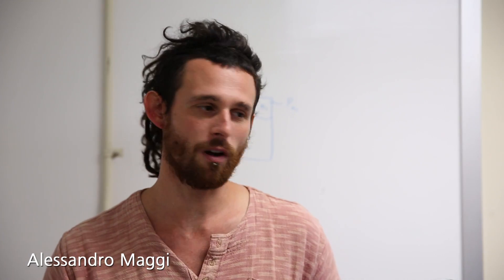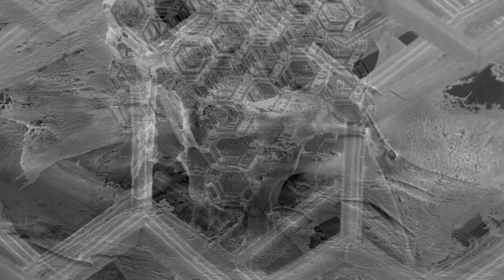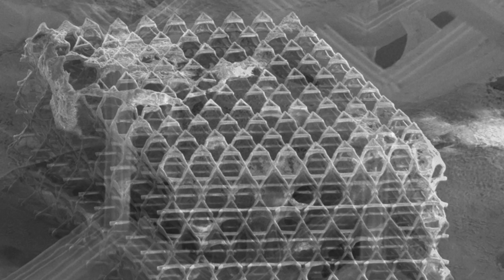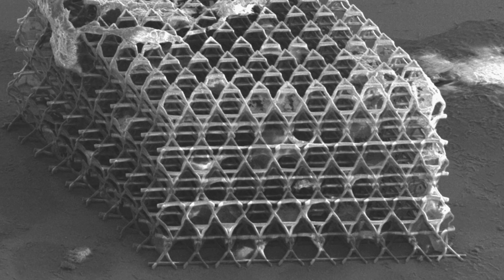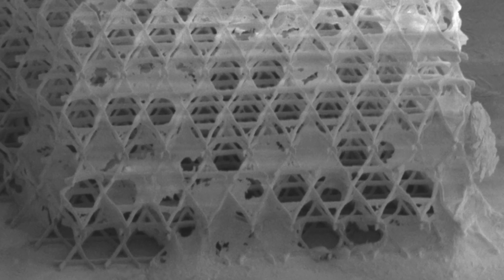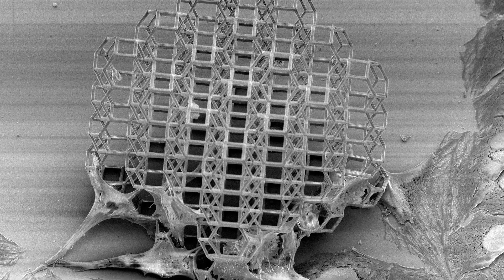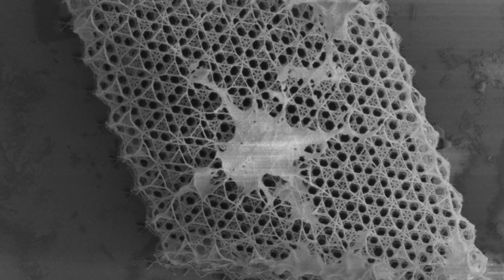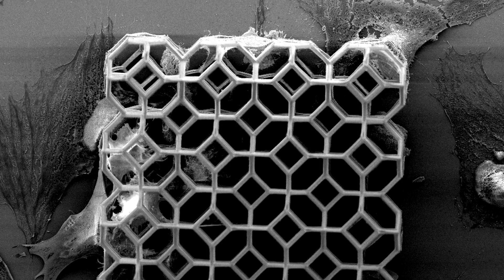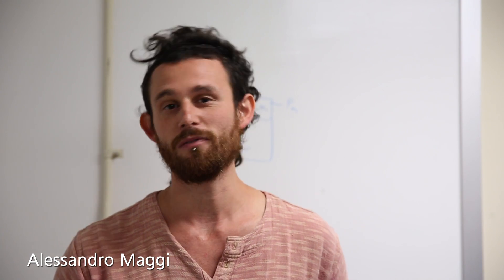One of my projects involves cellular solids and making nano-scaffolds for synthesizing organs — specifically, we're working on bones. Here's a Kagome lattice. This structure has been tested for bone growth: we coat it with a mineral that is present in our bones, and then we test the structure with real human cells. The structure performed quite well. We can control the geometry and try out different geometries and different materials to make these artificial scaffolds that one day, hopefully, will be implanted in human bodies.